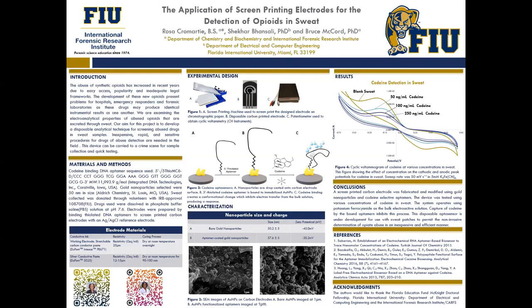And then this inhibits the oxidation and reduction of ferrocyanide due to the capturing of codeine, which causes the conformational change of the aptamer after binding. So it blocks the surface of the electrode from creating the oxidation, from creating the electrostatic electron transfer, charge transfer exchange.